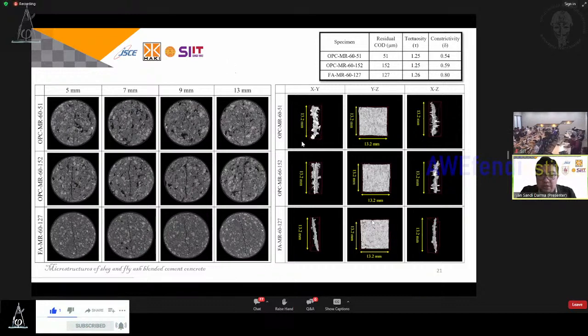And then after thresholding, we will have a crack geometry here. We will have a 3D of the crack. Here, as you can see, we evaluate tortuosity, I mean the straightness level, and the constrictivity. Constrictivity means the variation of crack width. For all specimens, the crack geometry is similar, around 1.2. Tortuosity is the straightness: a value of 1 means straight, higher than 1 means you have some tortuosity. And for constrictivity, a value of 1 means uniform crack width, but lower than 1 means you have a variation in crack width.